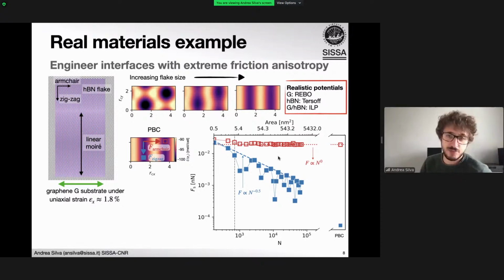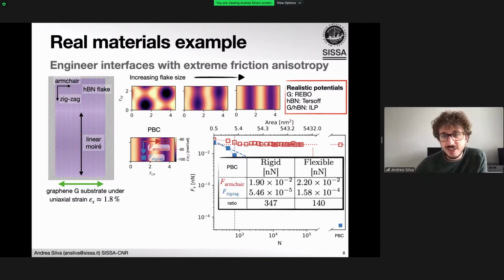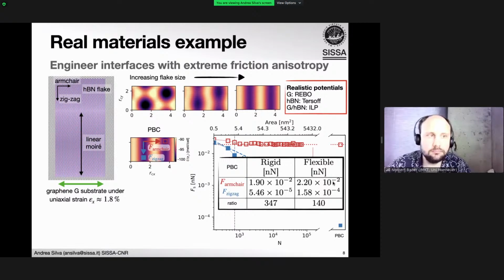The system has constant friction perpendicular to the valley and goes down sublinearly in the other direction, realizing in the infinite system a very strong anisotropy and structural lubricity only along one specific direction. Using numerical simulation, we can also probe the effect of elasticity, which of course affects the whole system, but this behavior is still retained.